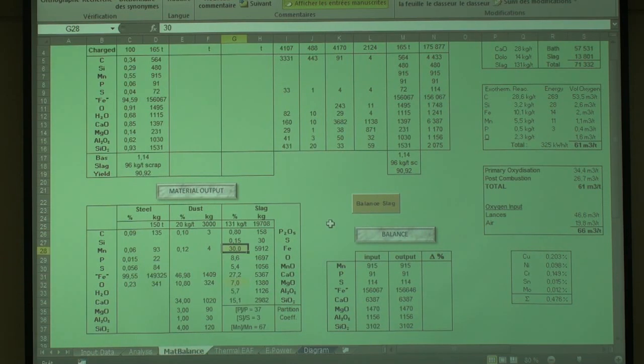Iron content is also a given figure, because it depends on the good practice of the operator. We could put, let's say, a thermodynamic equilibrium for the iron content depending on the carbon content. But what about the foaming slag? I was able to reach 100 ppm of carbon. Here, 100 ppm of carbon with iron content of 15% in the slag. Yeah? Which is far away from the, let's say, equilibrium between steel and slag.